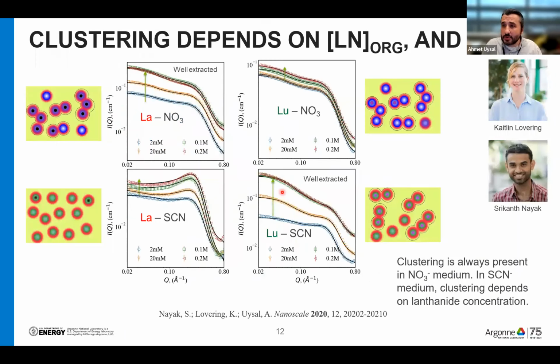If we extract metal ions, now I am demonstrating the metals with black dots at the center of these aggregates. And what happens is, with the nitrate system, the structuring doesn't change at all. You extract a lot of lanthanum, for example, they go in these clustered aggregates, but the overall structure doesn't change. The increase that we see here is only from the contrast because of the increasing metal loading. We don't extract any lutetium, very little. And again, this is very similar to what we have seen in all cases. The structure is the same, but there is no metal extraction. So it seems like the organic phase is not playing a significant role with the nitrate system.